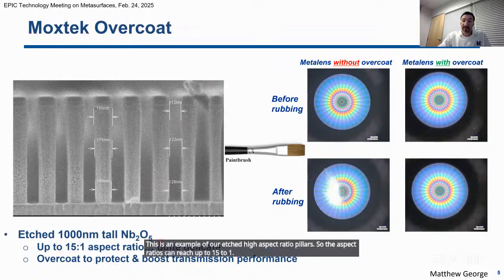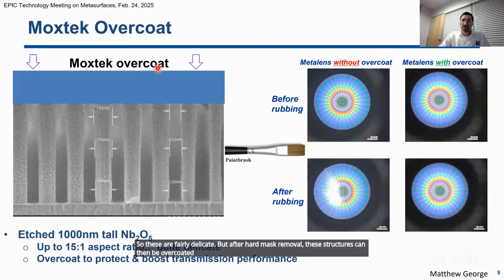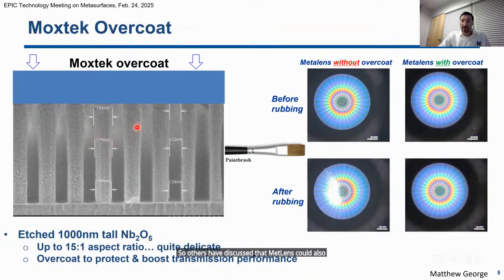So these are fairly delicate, but after hard mask removal, these structures can then be overcoated to protect against handling damage as shown here. So without overcoat, even a paintbrush can damage the Metalens surface, but with overcoat, there was no damage. And the overcoat can also act as an anti-reflective layer and boost transmission significantly. So others have discussed that Metalens could also be infilled with a low index material, but the advantage of our overcoat is it spans over the top of the pillars, maintaining the high index contrast between air and the high refractive index material, and maintaining reasonable aspect ratio requirements.